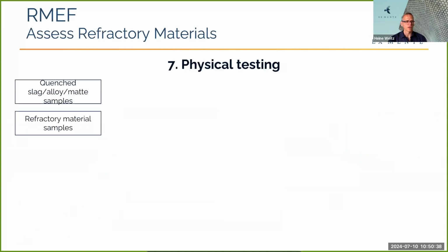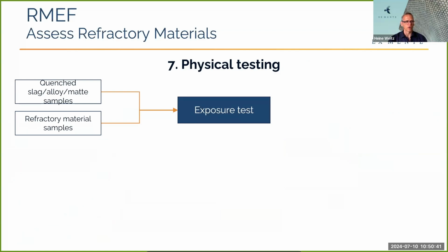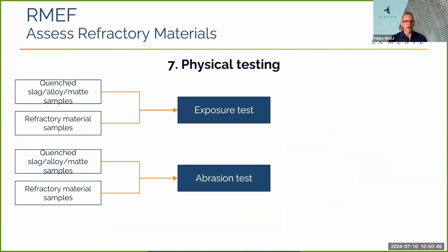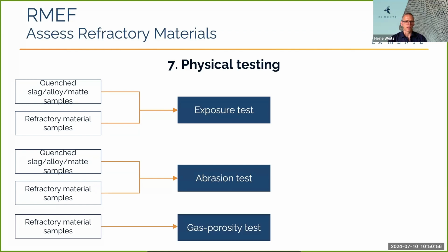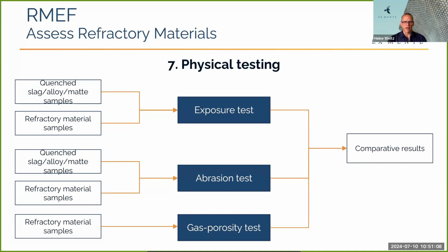Okay, and then finally, we can go to physical testing, where we take a product sample in contact with a refractory material at the conditions that you expect in the process and do an exposure test. And similarly, you can do an abrasion test, which involves higher flow velocities, and one can also do gas porosity tests, again, if gas containment is required in the freeboard. And at the end of the day, the absolute numbers are maybe less telling than the number compared to that of the existing material. So it's important to be able to look at the performance of an existing refractory material and compare that with a new material to see if the new material would outperform or underperform.